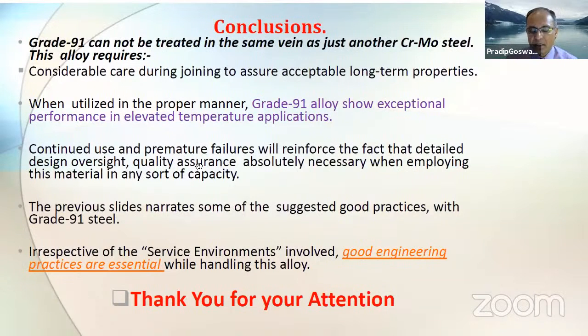Okay, so the issue is P91 to austenitic stainless steel or Inconel 600. Dissimilar metal welding is a burning issue, I would say. There are a few rules. In this case, it is a welding between P91 and an austenitic alloy. Austenitic alloy doesn't require any post-weld heat treatment, whereas P91 always requires post-weld heat treatment.